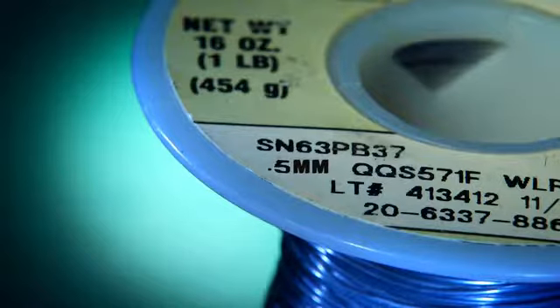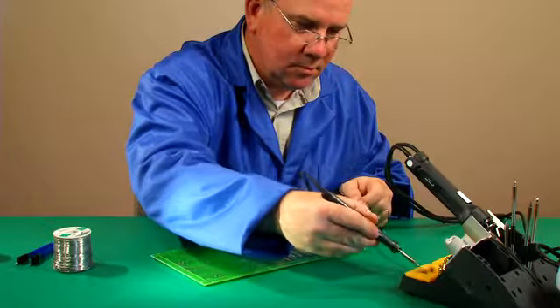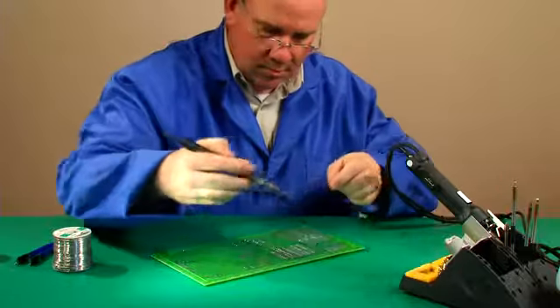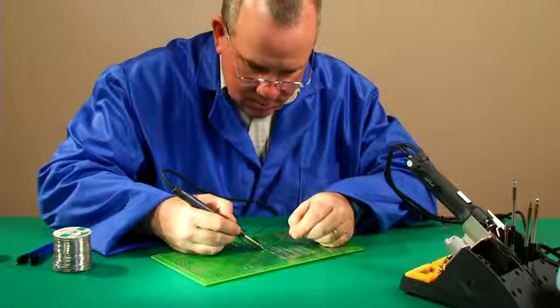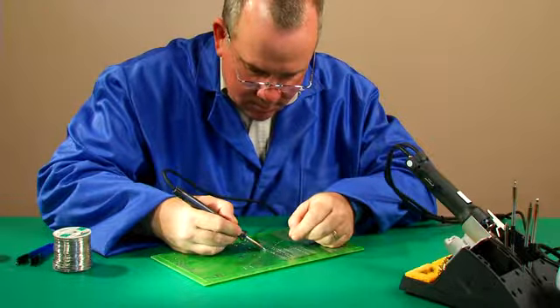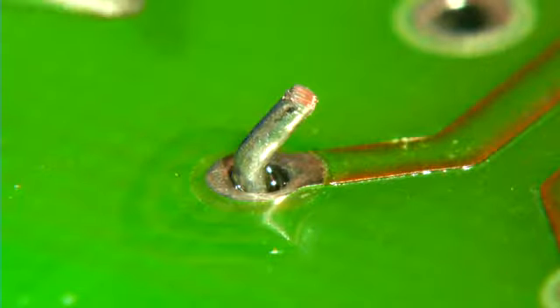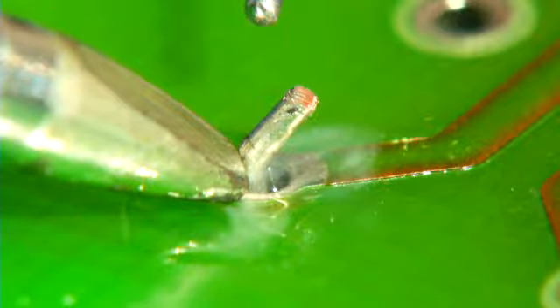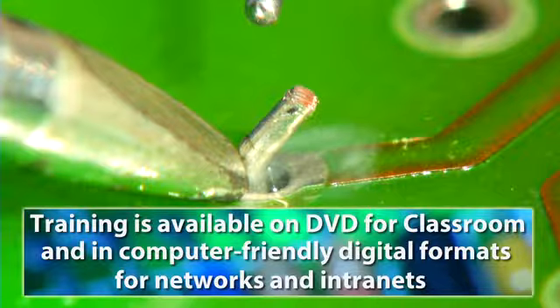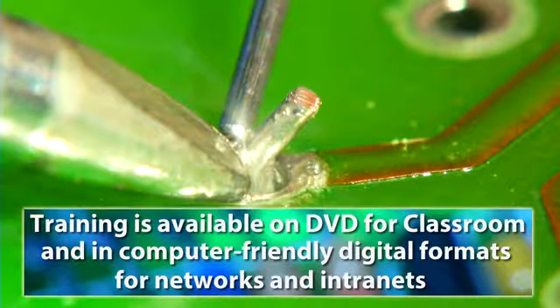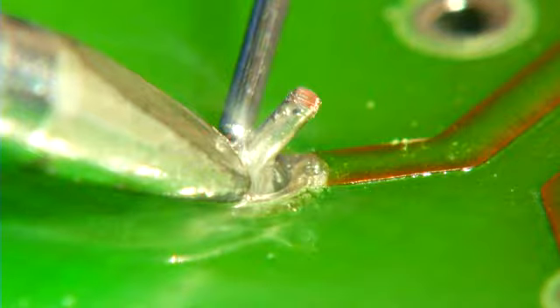Let's start with tin lead solder. Normally, this type of soldering operation would only take a few seconds to complete, but we'll be stopping the process in order to explain everything that happens as we go along. We begin by gently placing the cleaned and tinned soldering iron tip against the lead and the land. This will transfer heat into both of these parts. Now the solder wire should quickly touch the tip of the iron to melt just enough solder and flux to form a heat bridge between the metals.